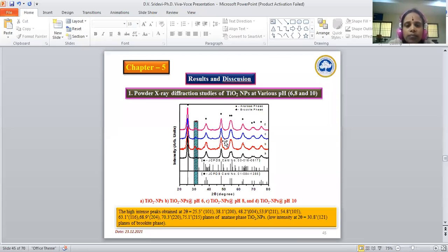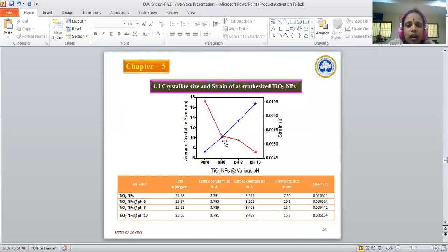In addition, the crystalline size of TiO2 nanoparticles was found to be 7.3 nanometer. When the pH value increases, the crystalline size of the TiO2 nanoparticles increased from 7.30 to 16.8. So the average crystalline size of the synthesized nanoparticles was found to be between 7 and 17 nanometer, which can be seen by plotting average crystalline size with the strain values versus the as synthesized nanoparticles as shown in this slide.